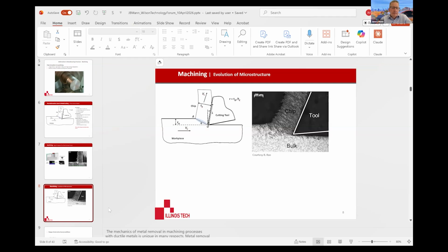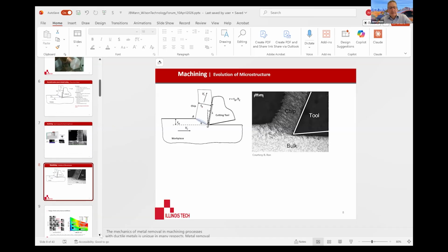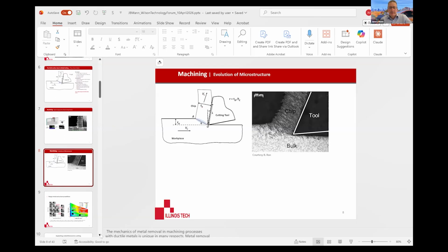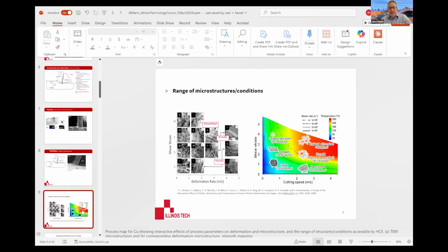So that's an interesting other aspect of the large strain in machining, is that we can now not only use it as a potential way to make materials, but we can also actually use it as a way to control the microstructure of those metals and alloys in a new way. And that's what this slide is showing, a range of the microstructures and conditions that can actually be achieved through machining. By changing the parameters of the machining process, the velocity and the rake angle of the cutting, or the shear angle, we can actually map a whole range of shear strain and deformation rates and essentially create different grain structures of, in this case, the chip.